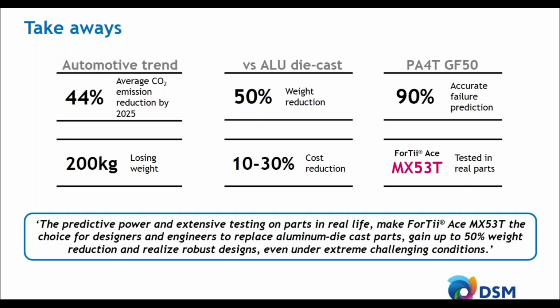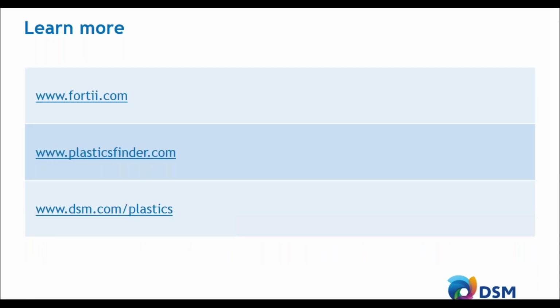We see that polyamide 4T with 50% of glass is one of the key materials that can be used to replace aluminum. Due to the fact that it has high chemical resistance, low and slow moisture absorption, and it's almost on par with the strength and the stiffness of aluminum, you can have a very robust solution. We are able to predict with around 90% accuracy, and we have tested the material extensively in real parts. So if you are looking forward to taking up that challenge, we have the right materials and also the right competences to help you with that.